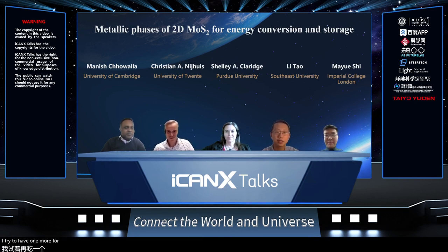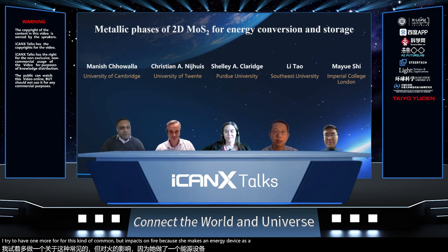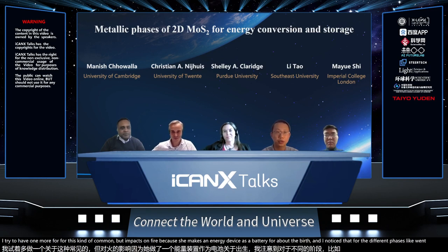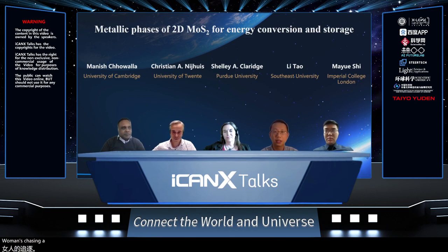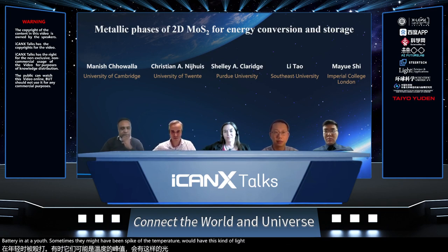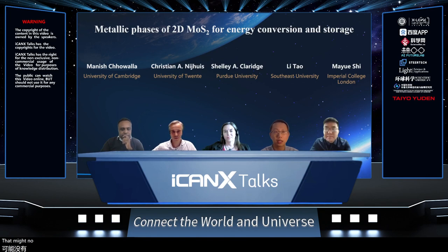So for this kind of molybdenum disulfide application, this energy device, let's say batteries or capacitors, I noticed that for the different phases, like 1T or 2H, they do have some significant performance change. My question is that during battery use, sometimes they might have some spike of the temperature, which could cause a phase change of the MoS2 that might degrade the material itself in the long run.